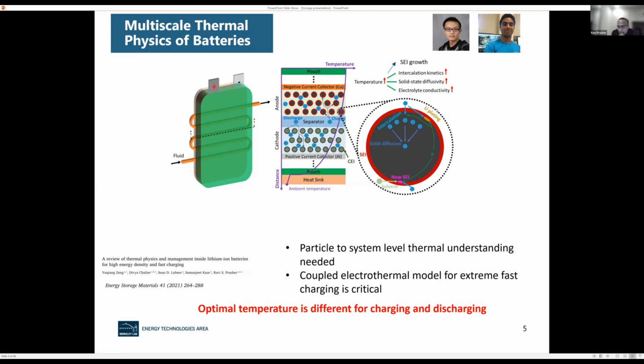So the temperature has a very interesting effect. On one hand, it increases the intercalation kinetics, okay? If you have higher temperature, solid state diffusivity increases. So in a way, for extreme fast charging, to avoid plating, you may want to increase the temperature. However, when you increase the temperature, it also increases side reactions and the SEI growth, right? So when you're discharging the battery, you want to bring the temperature down, right? So it's possible that the optimal temperature is different for charging and discharging, right? That offers a very unique opportunity in terms of thermal management.